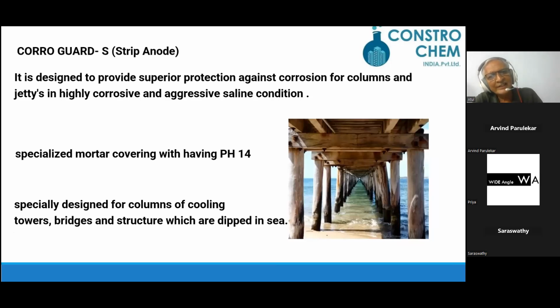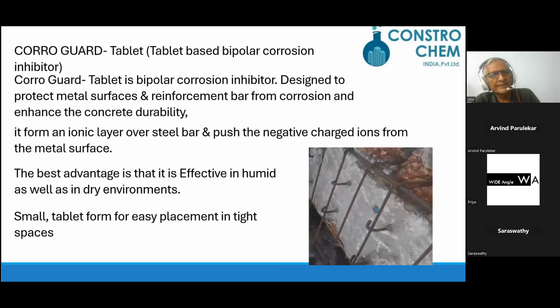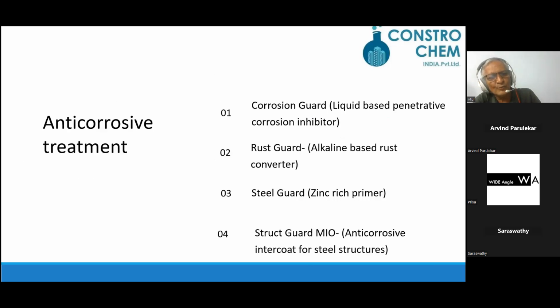Corroguard S is designed to provide superior protection against corrosion of columns and jetties in highly corrosive and aggressive saline conditions, a specialized mortar coating having pH 14, specially designed for columns, cooling towers, and bridge structures. Corroguard tablet is a bipolar corrosion inhibitor designed to protect metal surfaces and reinforcement bars from corrosion and enhance concrete durability. It forms an ionic layer over the steel bar, repelling the negative charged ions from the metal surface. The best advantage is that it's effective in humid and